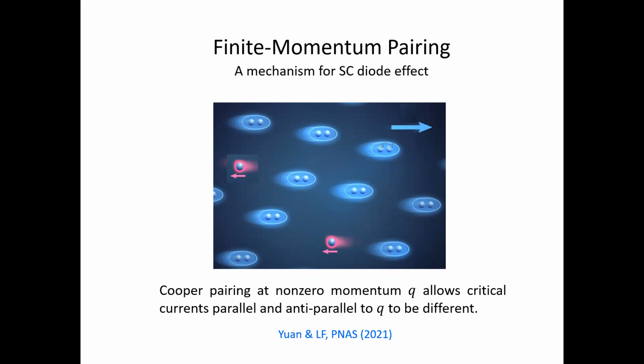So here's the schematic. In such a finite momentum superconductor, we basically have a condensate of Cooper pairs. But now the Cooper pairs have a finite momentum and therefore finite condensate velocity. Also, this superconducting state consists of unpaired quasiparticles because there's a spin imbalance. So there are leftover majority spin electrons that are unpaired, and they also generally have some finite momentum. Okay, so in equilibrium, in the ground state, the Cooper pairing has a finite momentum, but there's no net electrical current due to the fundamental Bloch theorem in solid state physics. In equilibrium, the ground state has no currents.